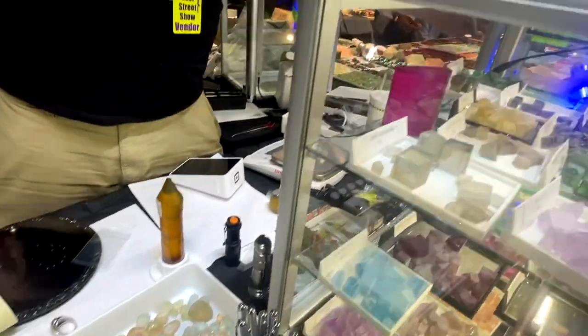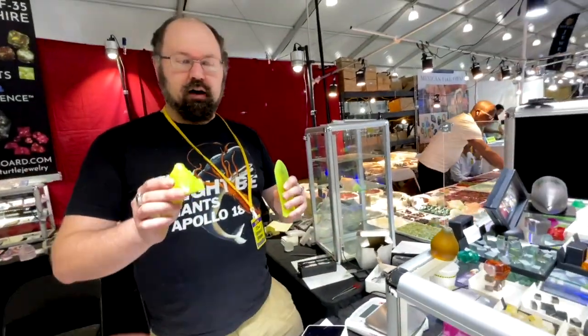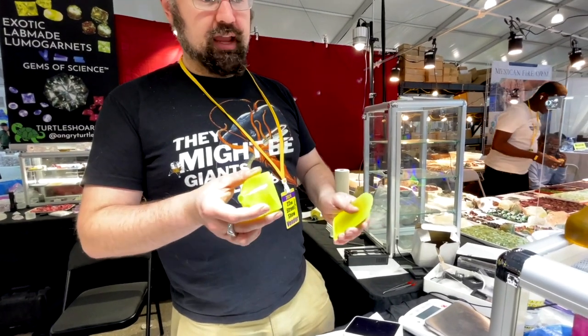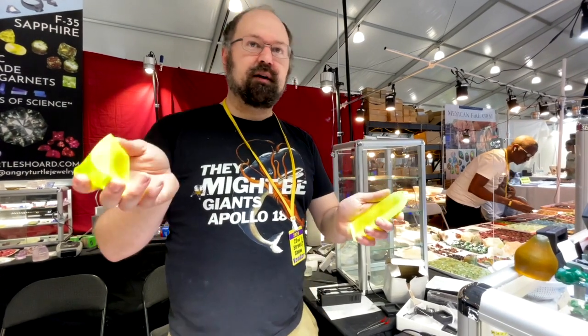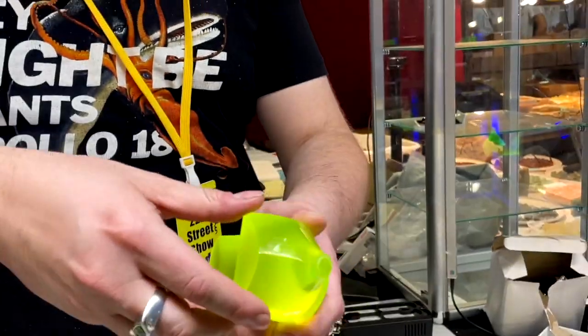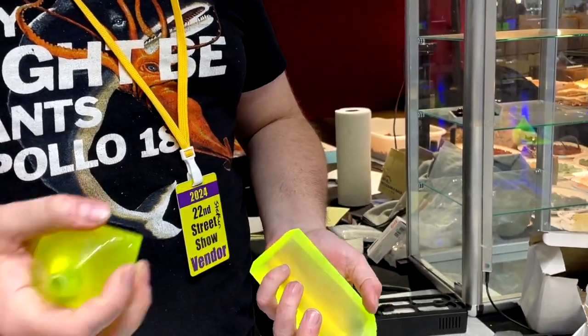These are just the rejects that didn't work in the laser industry? Yeah, we either get pieces that don't get specced, or we get the off-cuts. This is Lutetium Aluminum Garnet, or LUAG, and it's used in PET scanners — it's hyper-fluorescent and can detect gamma rays. The tops and sides, since they're in contact with the atmosphere, tend to be less pure and they can't use them. So we have a deal with the grower where they take the center part for medical equipment, and we get the tops and sides. We can repurpose these, and it just makes everything a little bit more efficient.